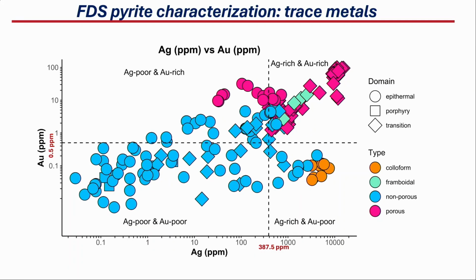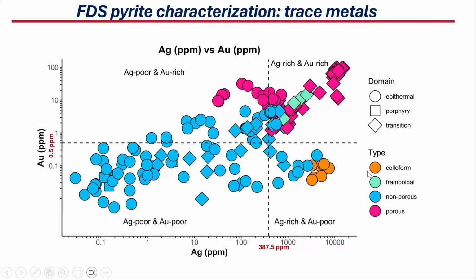Now we see the same diagram, but instead of showing the areas, we show the domains. I separated them into porphyry, epithermal and transition zone. So we see that again, non-porous pyrite from the different environments is gold and silver poor. But we see that most of the porous pyrites in Aurora are from the transition zone between the porphyry and the epithermal. And here the colloform and part of the non-porous pyrites are from the epithermal itself.